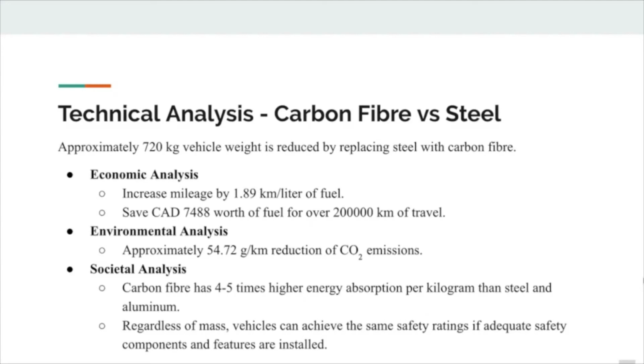With regards to the societal impact of weight reduction, the safety of a vehicle does not actually depend on its weight but rather depends on its footprint, which is the area between the four wheels. Lightweight vehicles can still be safe if they have footprints within the safety standard and are made of high energy absorption materials. Under an impact, carbon fiber has 4 to 5 times higher energy absorption per kilogram than steel and aluminum. High energy absorption leads to reduced impact time and consequently minimizes injuries to the passengers.